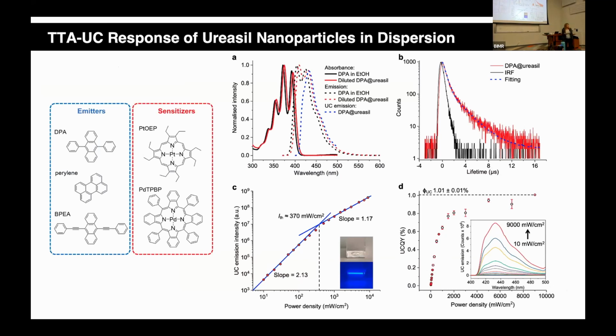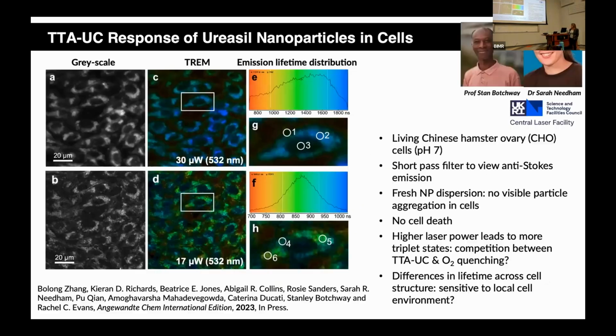So we're getting our up conversion from our nanoparticles. As for any TTA-UC process, the emission intensity is highly dependent on the power density of your excitation source because it's a multi-photon process. So we can see really that the up conversion quantum yield is really quite low, but it depends very much so on the power density. So we need to get to reasonable power densities before we get a quantum yield of around 1%. This is quite low, but it's certainly adequate to do imaging microscopy with. And so that's what we did.